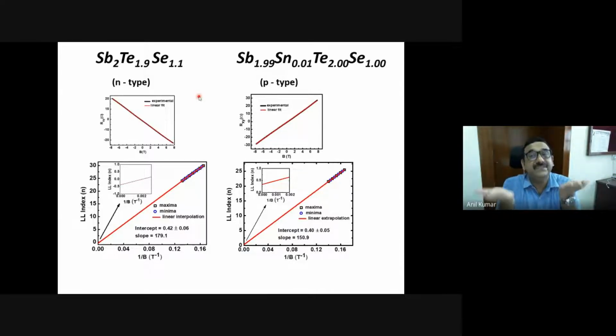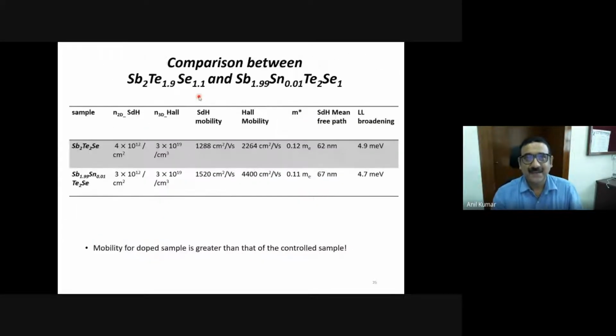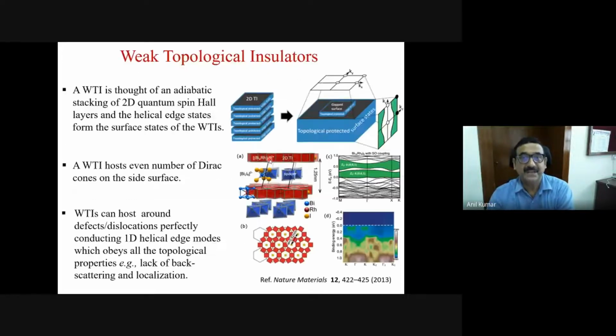Now I have 2 different materials. One is N-type, other one is P-type. So now the experiments which we are doing is that we are exfoliating one on top of the other, and we are looking at the junction properties, p-n junction properties, of this topological insulator combination. So, I mean, very interesting results. You get the Hall mobility from these SdH oscillations, the oscillation which I showed you earlier. You can extract the mobility of the sample. So it's a very good sample with a very good mobility.